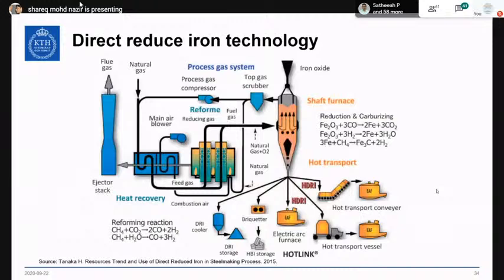To reduce the emissions in the steel plant, there is another technology called the direct reduced iron technology, which uses natural gas instead of coal to reduce the iron ore. So your natural gas reduces the iron ore that is fed from the top, and then that forms sponge iron, and that sponge iron is fed to the electric arc furnace. Now, this has been clearly seen even in power plants, that a shift from coal to natural gas reduces the amount of CO2 emissions for the same amount of energy output. Again, using natural gas here reduces the amount of CO2 emissions in the steel making process itself as well. I'm not going to go too much into the technology itself here.